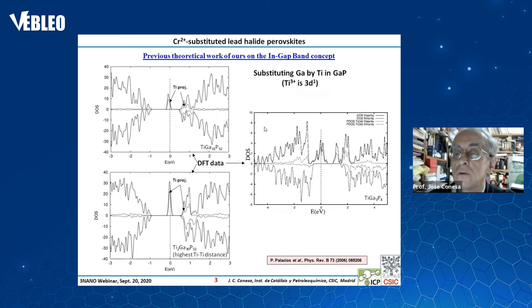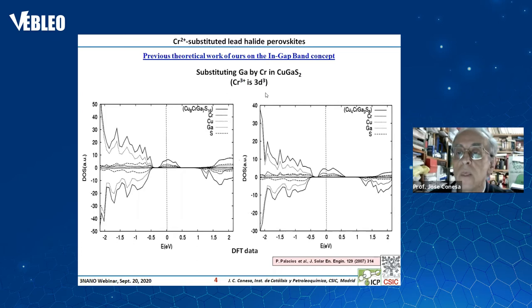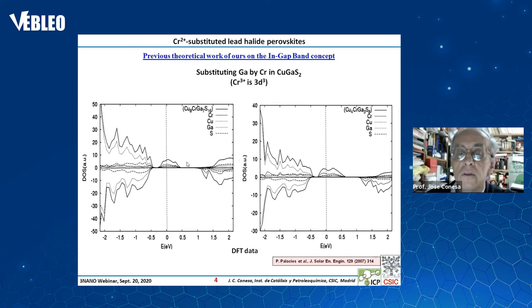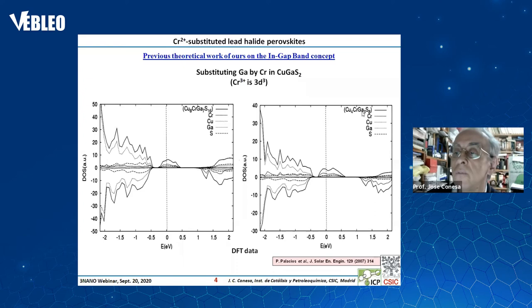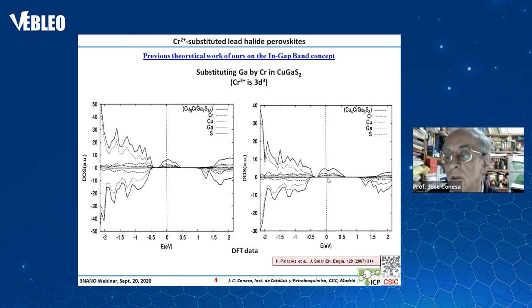It is also possible to make the substitution — in this case by chromium, also of gallium — in the chalcopyrite copper gallium sulfide. In this case, you can see that again we have an ingap band which is partially filled by electrons, because this is again the Fermi level. Even when you increase the concentration of chromium, the width of the ingap band does not increase too much, so it is possible to maintain the good situation even at high chromium concentrations.